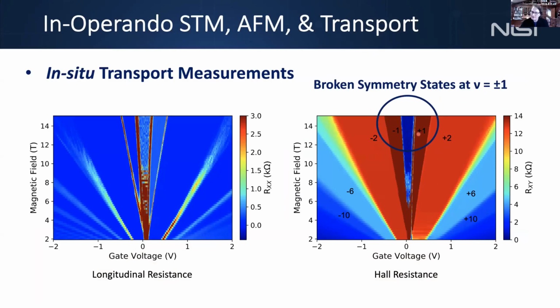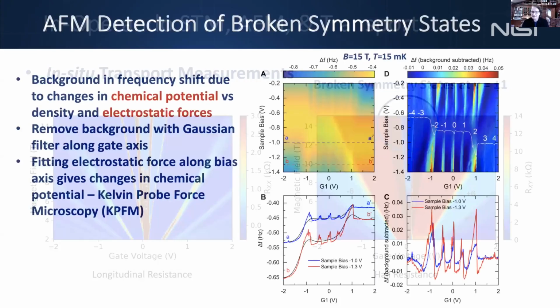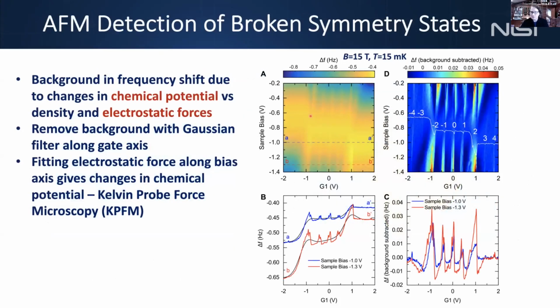So we want to see how we can see this in local measurements. You could see this in STS measurements if you have the right conditions, but we wanted to see, can we see this in AFM measurements at these temperatures and at these fields? And the answer was yes. To our surprise, we were really excited. This is actually some of the first data that came out of the measurements. This is a frequency shift map. The AFM cantilever is changing frequency because of the force changing due to the broken symmetry state. Okay, so you see these spikes here. This is the same region where the broken symmetry states occur.